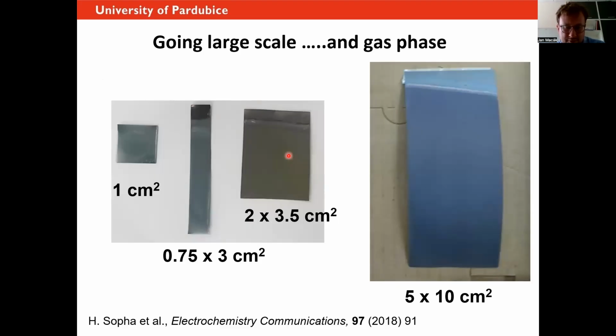And this brought us to the, let's say, last information that I want to convey today. And that is another challenging task. And that is making the tubes on a large area. And I mean really not square centimeters, but if possible, square meters. Because we just learned that the tubes have very good photocatalytic rates, but it's not just that, they're actually very good in many other things. And therefore, it would be handy to have these tubes grown on titanium of substantially larger area than 1 square centimeter. But this is a similarly high challenge as with the shortening of the anodization. Remember the lactic acid. So for me, this is the same importance, because we really push the limits of the technology here, and we show what is possible, and we try to really step over the boundaries and push the boundaries.